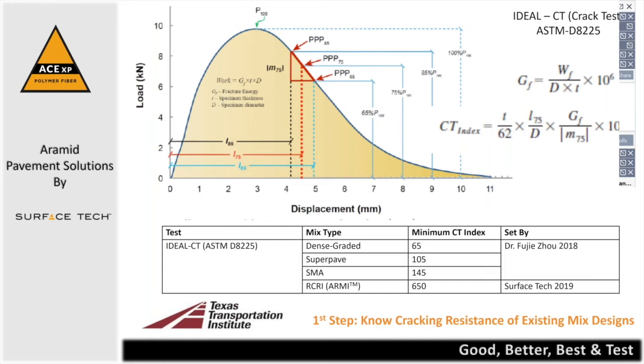Oh, yes. As a matter of fact, the National Center for Asphalt Technology, NCAT, down in Auburn, has now done quite a bit of work on ruggedness testing, and that's now being added to the standard. I actually had a chance here in this lab to begin doing some testing in warmer climates where we've tested at 35 C. I've got a lot of faith in this test, Joe, and Fuji continues to work on this, in addition to what he calls an ideal RT for rutting too. So far, so good, Joe.